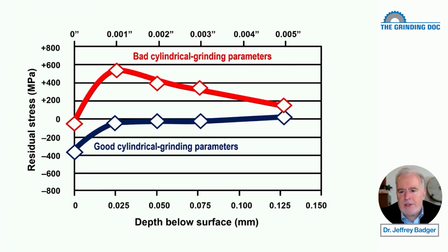And what I teach my customers in my course, the grinder's mantra is: big and dull, bad; small and sharp, good. Big and dull, bad; small and sharp, good. We want our wheel to have small, sharp grits instead of big, dull grits. So we got that. We found a 120 mesh wheel. We dressed it sharp. Then the next thing was the overlap ratio in cylindrical traverse grinding.